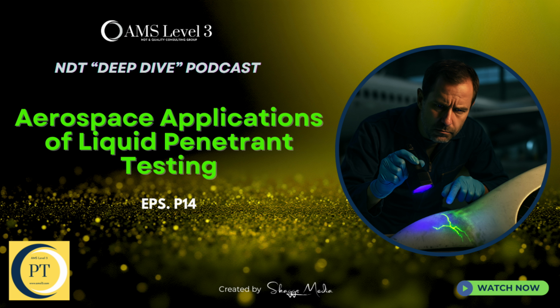And the daily checks, that's like the inspector's pre-flight checklist. Exactly. It's their ritual. Daily checks confirm the overall system performance. They check the penetrant and developer baths for any gross contamination. They check the condition of the dry developer. And the inspector absolutely must confirm the UV radiation intensity at the part surface and verify the cleanliness of the whole area. If that UV light is dim, you can't proceed. You cannot proceed. It's a safety violation and a huge detection failure risk.